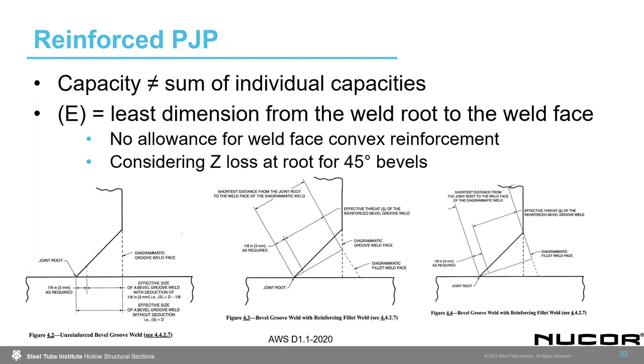Another option, if a partial joint penetration weld is not quite enough, again, to try and avoid going to that complete joint penetration weld, we can reinforce a PJP. That's definitely an economical option. The capacity of that reinforced weld does not equal the sum of the individual capacities. Again, we should specify an effective throat, which will be the least dimension from the weld root. Those are given by these great diagrams that I know are probably a little bit difficult to see on the screen, but can easily be found in D1.1 in Figures 4.2 through 4.4. The important thing here is that we need to be considering the Z loss at the root for the 45-degree bevels as well when designing these.